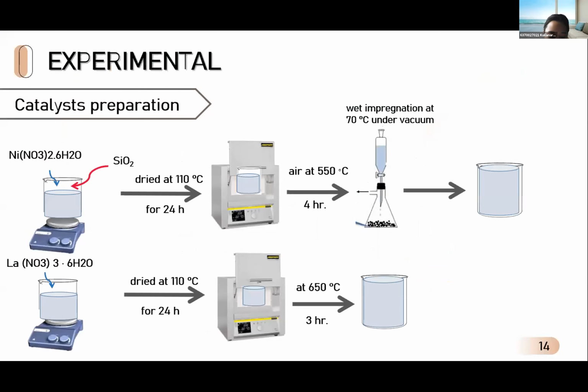The experiments. The first step, prepare the catalyst with wet impregnation at 70 degrees Celsius under vacuum using an aqueous nickel nitrate hexahydrate and silicon dioxide. The solid is dried at 110 degrees Celsius for 24 hours and subsequently calcined in air at 550 degrees Celsius for 4 hours. Using lanthanum nitrate solutions, the solids obtained are dried at 110 degrees Celsius for 24 hours and calcined at 650 degrees Celsius for 3 hours.